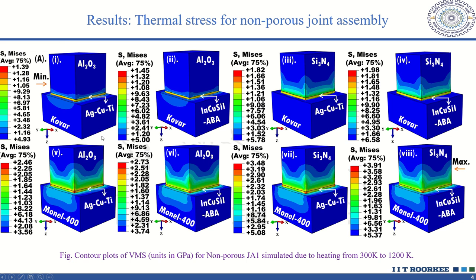So, the thermal stress for heating the joint assemblies for different material combinations is estimated and contour plots are plotted. The results show that the von Mises stress increases from left to right and top to bottom. This is because the CTE parameter, or coefficient of thermal expansion, is an important parameter for the joint performance. As we are going from left to right, the CTE mismatch is increasing in these material combinations, and so the von Mises stress or thermal stress is increasing, and the same holds as we go from 1 to 5, 2 to 6, 3 to 7, and 4 to 8.